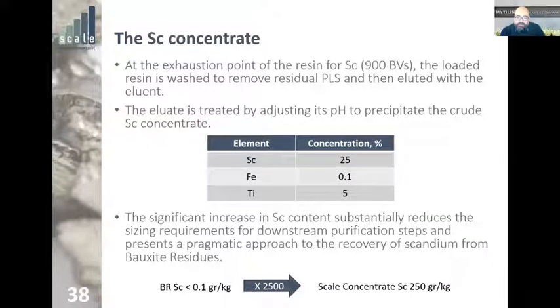And this concentrate had 25% elemental weight of scandium, 0.1% of iron, and 5% of titanium. So we have managed from a bauxite residue containing less than 0.1 grams per kilogram to go to a concentrate that contains 250 grams per kilogram. That's a 2,500 times increase. And this is the first viable candidate for recovery of scandium from bauxite residue, right? So since we got to hundreds of grams per kilogram, this can now work with the established solvent extraction processes to produce pure scandium.